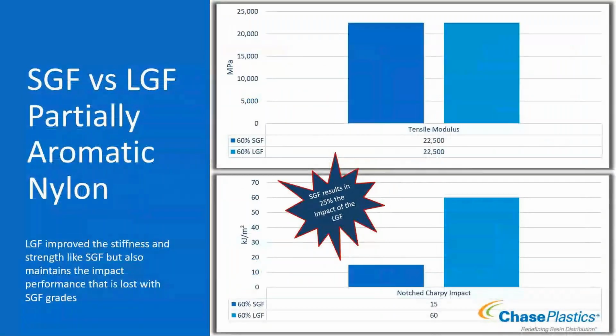And then of course, some data to back that up. If we're looking at short glass versus long glass, this is a partially aromatic nylon, so already a specialty nylon. You can see the modulus there—this is the stiffness of the material at 60%, heavily filled with these glass fibers. The modulus between the two is actually the same. For this particular aromatic nylon, at 60% short glass and 60% long glass, your modulus is the same—it increased, and it's the same for both.